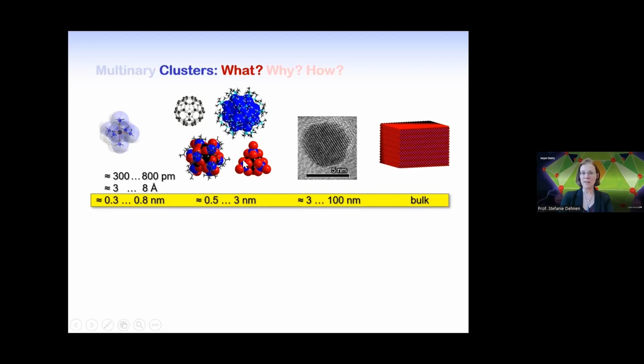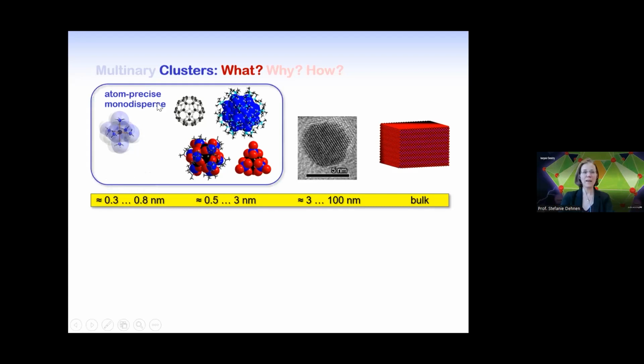So the largest clusters are not on this slide. The largest clusters I know of that have been crystallographically determined with specific atomic positions that you can really define are in the range of some 400 atoms, maybe 400 or 500 atoms. Then you are really at the end of what is doable for atomically precise molecules, and everything that is not clearly precisely defined, as you can see here, would be something I would call a nanoparticle. Yet I have to admit that this is probably also a matter of interpretation and a matter of taste. A cluster in the size of 3 nanometers could also be called a nanoparticle, but then it's a nanoparticle with atomic precision. So here you are in a range where you need a bit of definition, and you should probably have this definition along with your publication to be clear.